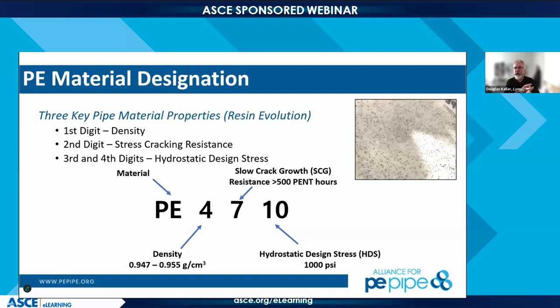So as we showed when we were dragging that pipe around the corner, we're going to get some scratches to the material. There's going to be some stresses that are applied during the installation process. All of that basically backs it down. So we have reduced very conservatively the stress that the material could handle over a long period of time. And that's where we get that 1,000 PSI that we start with as part of our design.